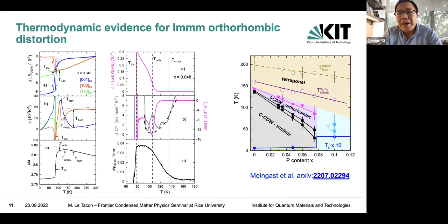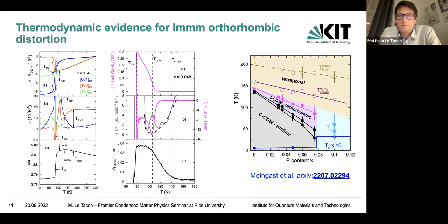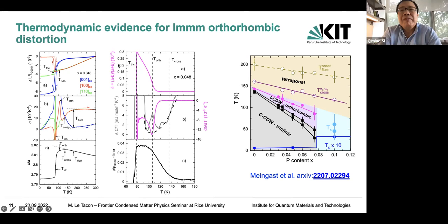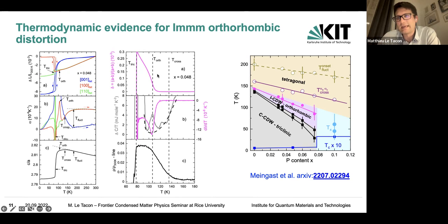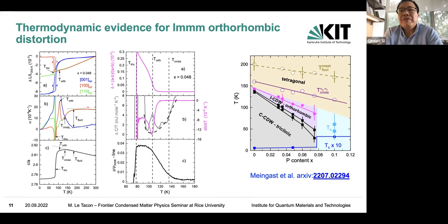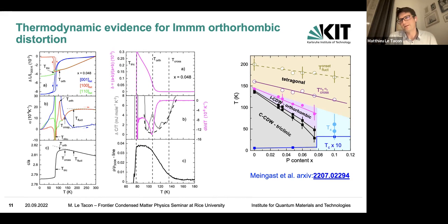Sure. But what's very clear, and maybe it's already an answer, is that the distortion here is insanely small. It's 10 to the minus 4, and if you look at the CDW peak, the superstructure satellites that we see in the X-ray diffraction are as intense as the nearby Bragg reflection. So for a very serious CDW, you do have a very tiny lattice distortion. So maybe that already answers.